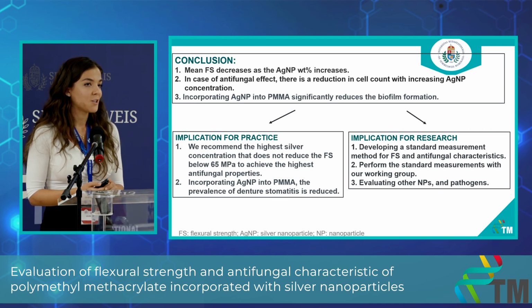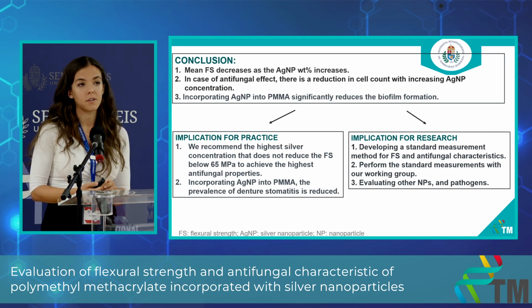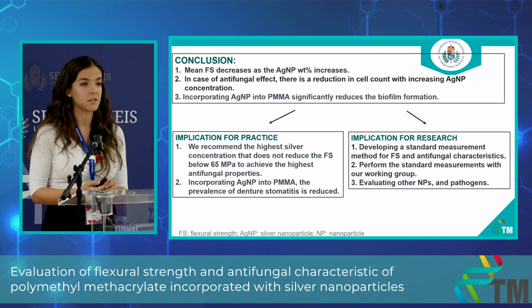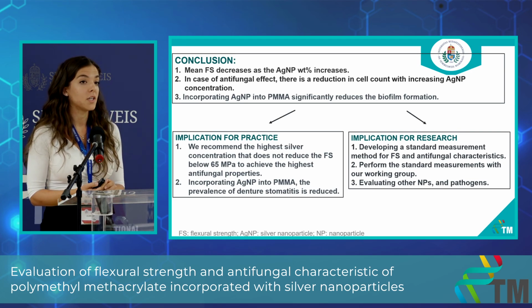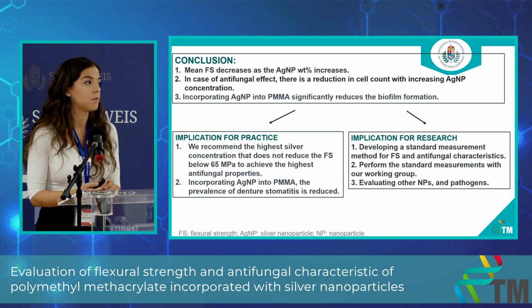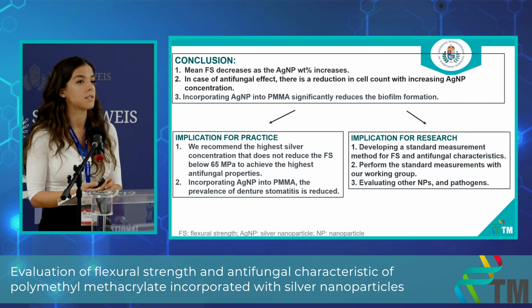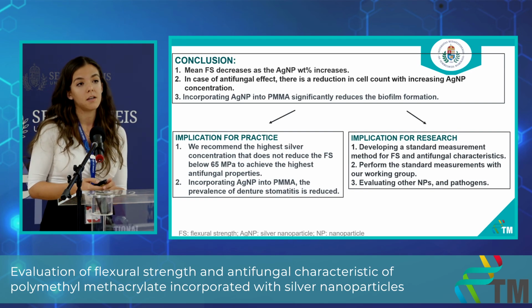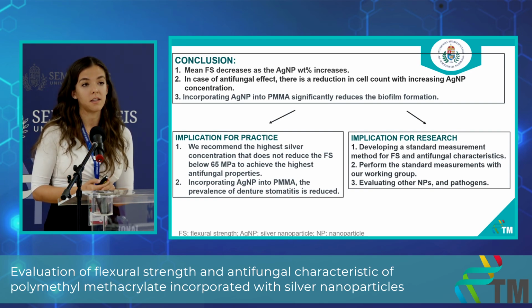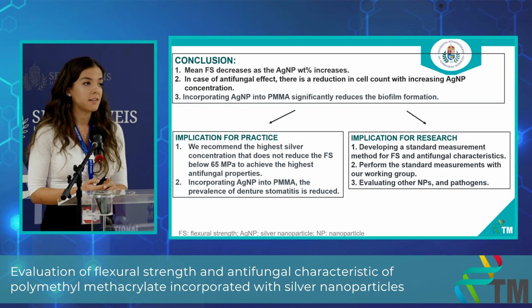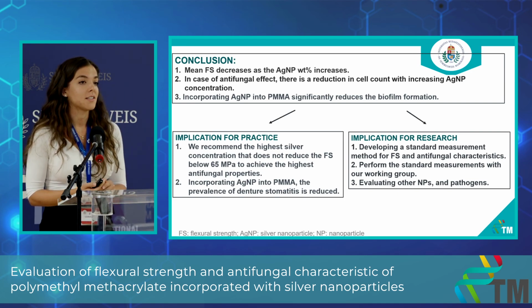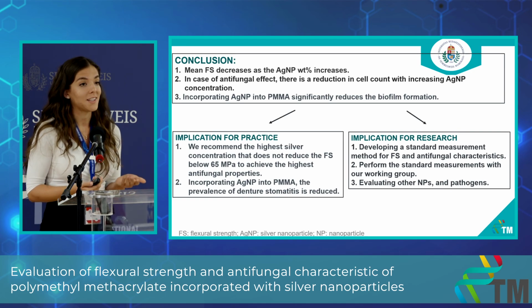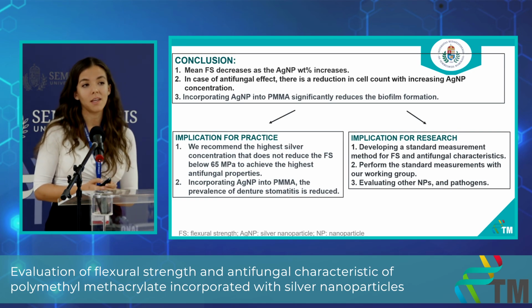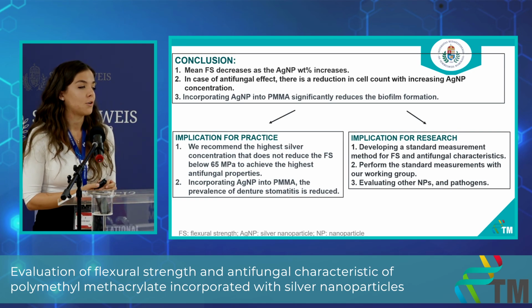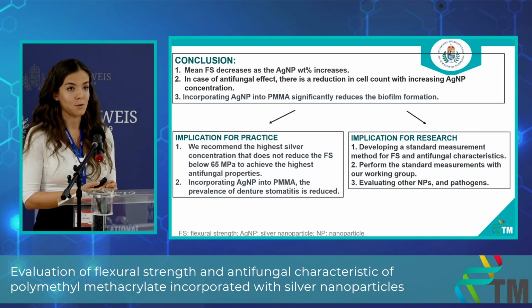We have some implication for the practice. We recommend the highest silver nanoparticle concentration that does not reduce the flexural strength below the ISO standard, which was 65 megapascal. In this way, we can achieve the highest antifungal properties. And the other implication is that by incorporating silver nanoparticle into PMMA, the prevalence of denture stomatitis is reduced.